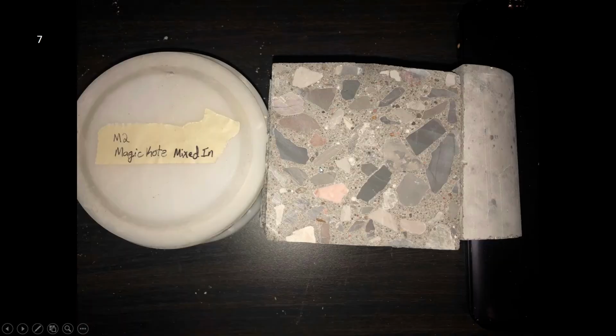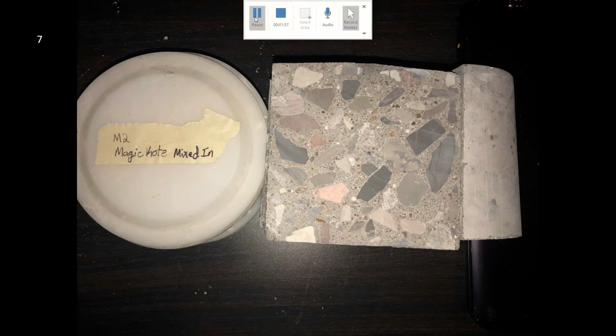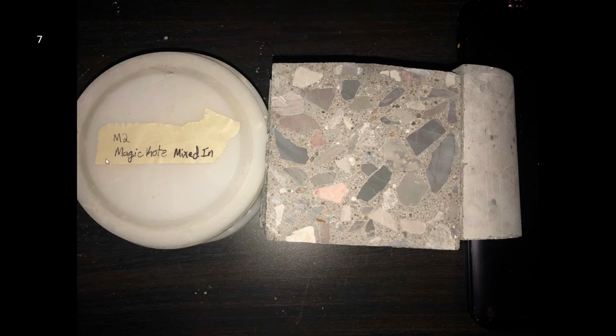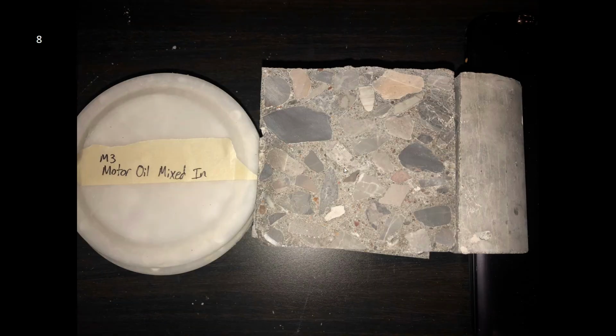Our seventh sample is magic coat mixed into the concrete. Now, you can't tell a difference with the surface area, and you can see relatively no difference with the cross section. Our eighth sample is motor oil mixed in with the concrete.